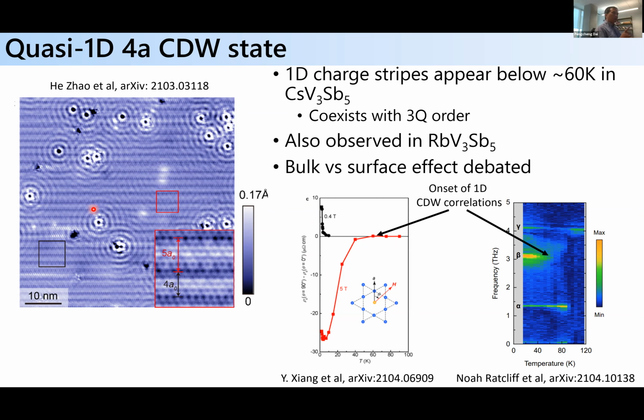Hey, Stephen, does the Raman scattering measurement suggest that you have a new optical phonon mode at 3 terahertz? Is that the story? Right, that's a good question. Yeah, I guess I didn't mention there is a Raman paper where they also see the same effect. This is basically time domain Raman, and he's just Fourier transforming it, right? This is transient reflectivity. But yes, Raman sees the same thing, and so I think in both cases it would mean there should be some broad optical mode, I guess, if it's coming from a lattice component. Yeah, maybe like a very short lifetime kind of optical response.